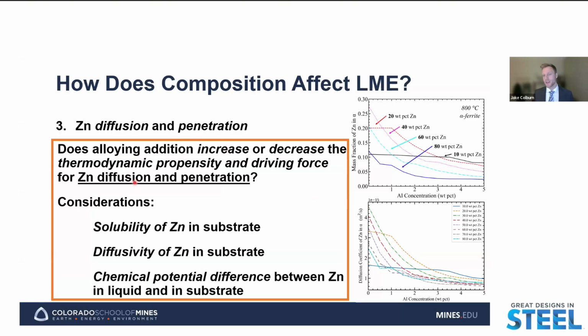And the considerations there that we can look at are, again, two of the ones that we looked at today: looking at the solubility and diffusivity of zinc in the substrate, but then also, even more fundamentally, looking at the driving force for diffusion being the chemical potential difference between zinc in the liquid and zinc in the substrate, and how that alloying addition plays into that chemical potential difference, even how that alloying addition, when the substrate is under stress, is going to affect the chemical potential difference there and the overall driving force of zinc diffusion.